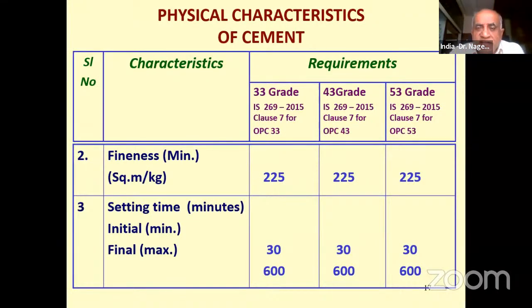Other than strength, we have fineness. Fineness is 225 meters square per kg. This is nothing but if you take 1 kg of cement, the surface area of the particles should be 225 square meter. So it's very difficult to find out the area of particles, but we have Blaine's method. Using that Blaine's method, we find out the fineness of the cement.